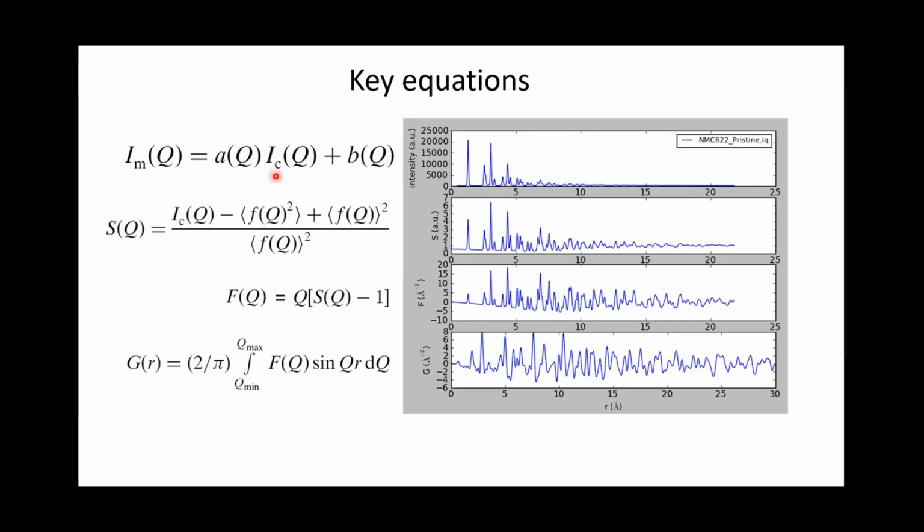Think about it. When you hit your sample with an X-ray with a wavelength of typically 0.18 Å, which is really high energy, then for us, if we simply measure transition metal oxides, they are almost transparent to such high energy X-rays, with a very small amount of absorption. But anyway, absorption comes into play, and there are also other processes such as multiple scattering. For the scattering, typically we discuss a single scattering event, but there can be multiple scattering events that will also dampen the intensity you will see.